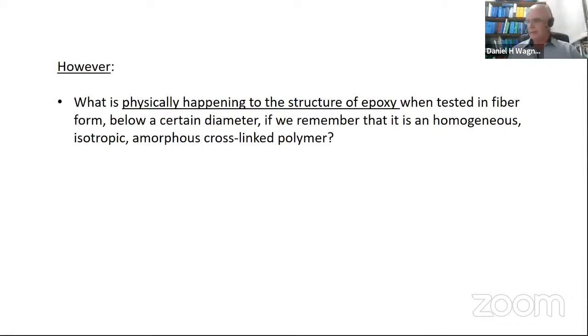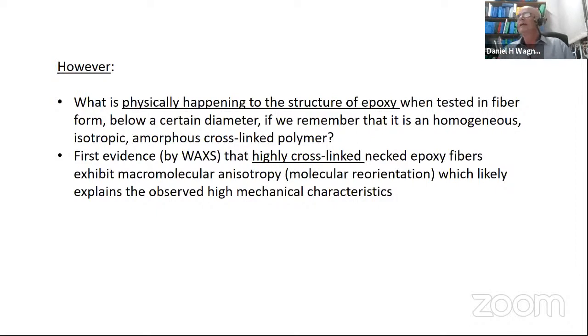The question I'm asking once again is what's going on? What's physically happening to the structure of epoxy, which is a cross-linked material, when it's tested in a fiber form below a certain diameter? And if we remember, especially, that it's a homogeneous, isotropic, amorphous, cross-linked polymer. So what's going on in epoxy, which is amorphous and cross-linked? We then did WAXS, which is wide-angle X-ray scattering. And we got the first evidence that these highly cross-linked necked epoxy fibers do exhibit macromolecular anisotropy, partial reorientation of the molecules, and that likely explains the observed mechanical characteristics.